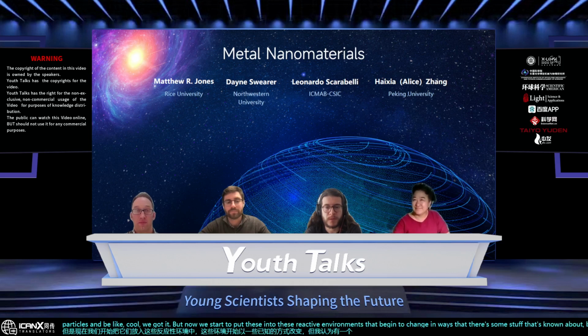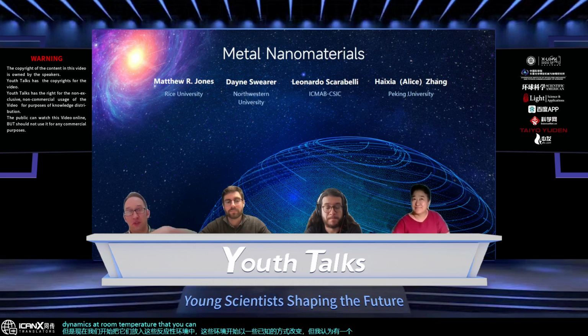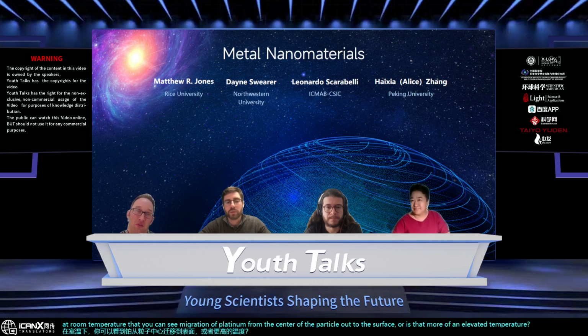Certainly. Do you have that much dynamics at room temperature that you can see migration of platinum from the center of the particle out to the surface, or is that more at elevated temperature? Elevated temperatures, yeah. This would be like in a CO atmosphere at 400 degrees Celsius or something. They'll migrate out quite a bit.